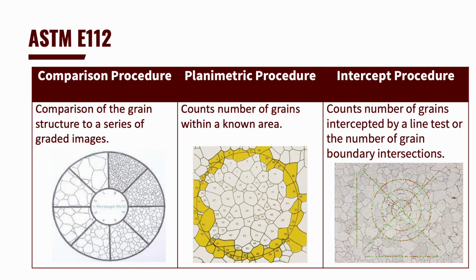Here are the three standard procedures of ASTM E112 presented in the table below. The comparison procedure performs a visual estimation of the grain size by comparing a live image to a micrograph chart. Grain size estimations need to be made with 3 or more representative areas of each specimen section. The comparison procedure only applies to recrystallized materials with equiax grains, which is why there is a problem with the standard ASTM for defining columnar microstructure in AM materials. The planimetric and intercept methods are always applicable for determining average grain size. However, the comparison charts cannot be used for measurement.